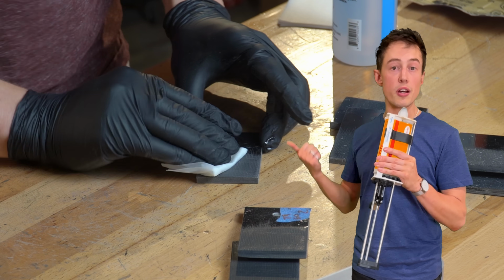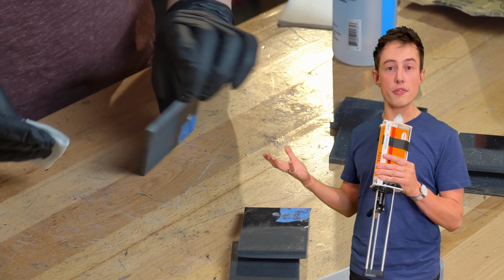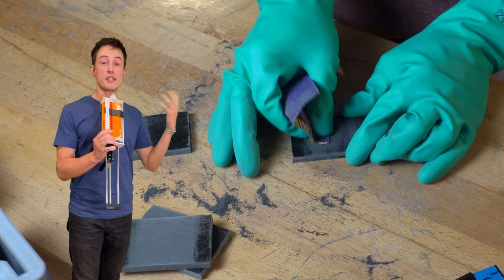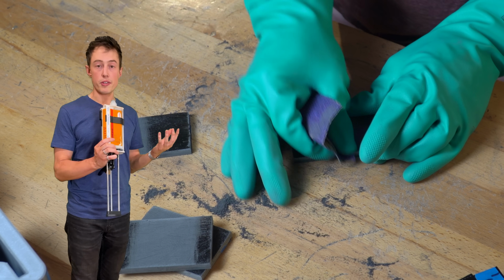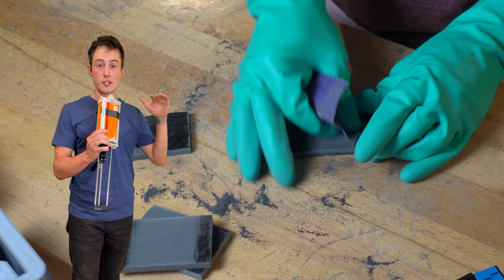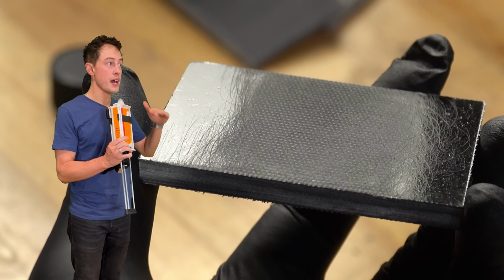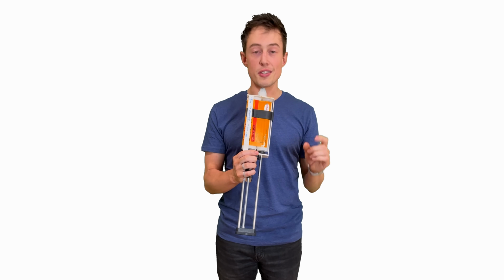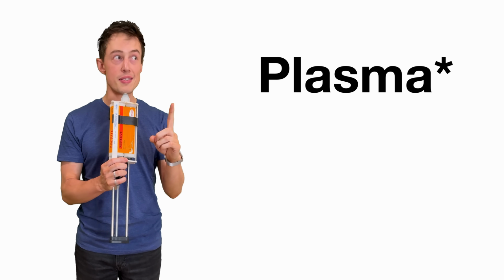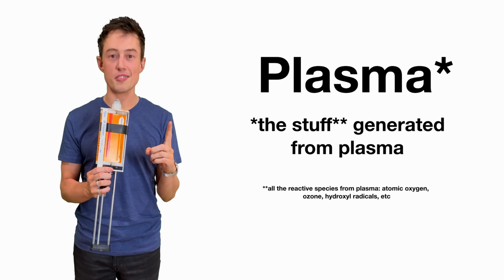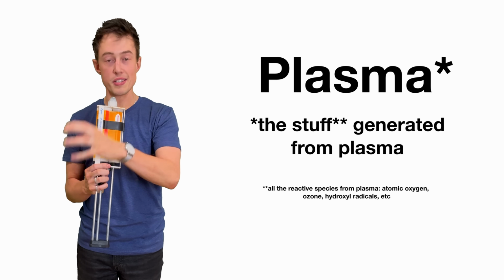Using solvents to clean off contaminants on the surface can break some of these bonds and raise the energy a little bit. Sandpaper breaks these bonds almost by definition. When we're etching until the surface is completely gray, we can be sure that we've etched away to fresh material. But there's another way to do it. You can also use plasma, and specifically the atomic oxygen that is generated within the plasma discharge.